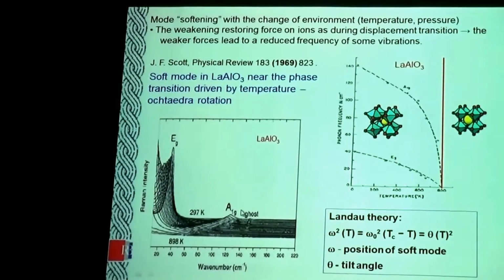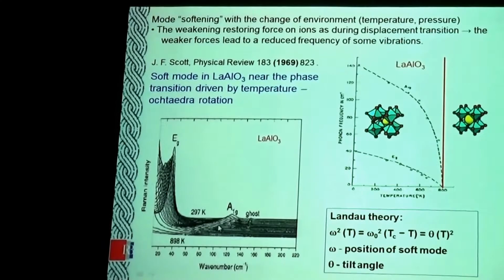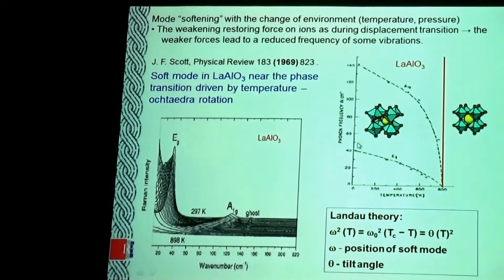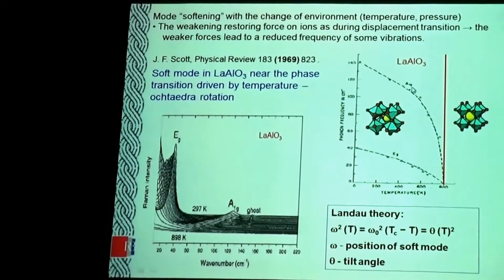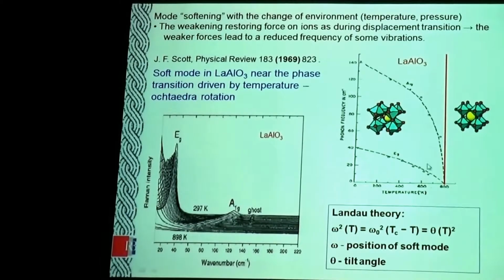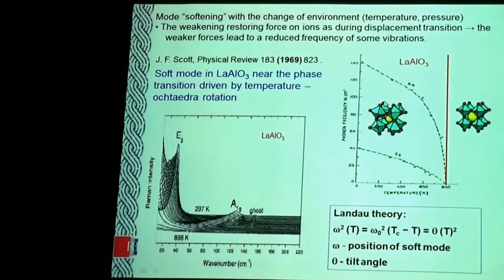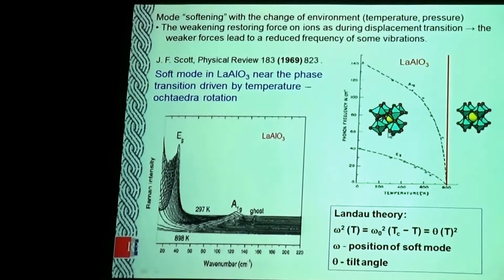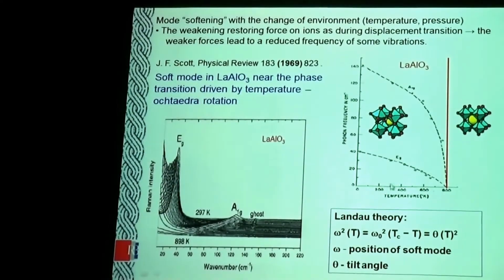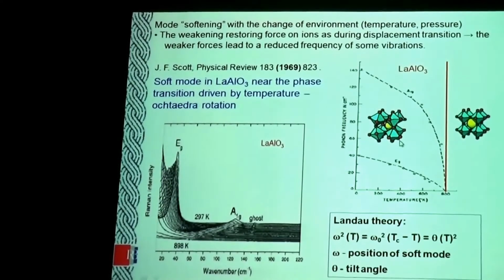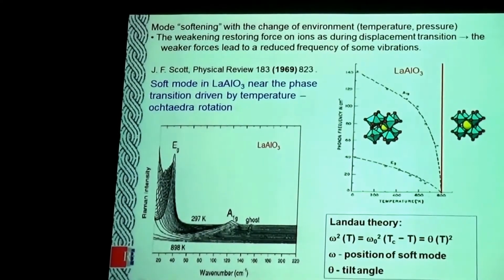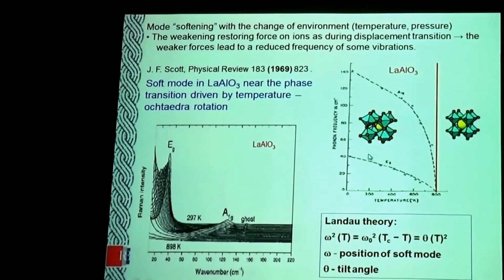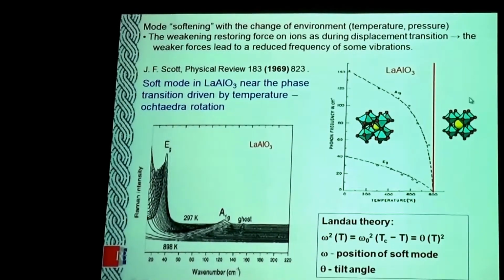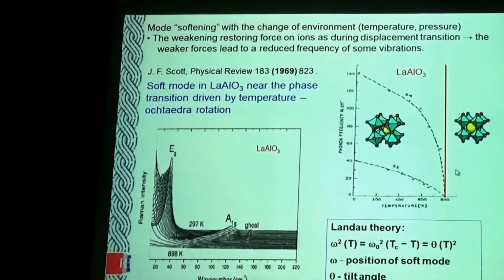The authors checked the shift of the modes during heating of the sample, and observed that their Raman bands shift to lower wave numbers during heating. At the same time, the structure changes, so the tilt angle in the crystal changes. They even calculated the tilt angle at every temperature, and after 800 degrees centigrade they got the cubic structure of lanthanum aluminum oxide.